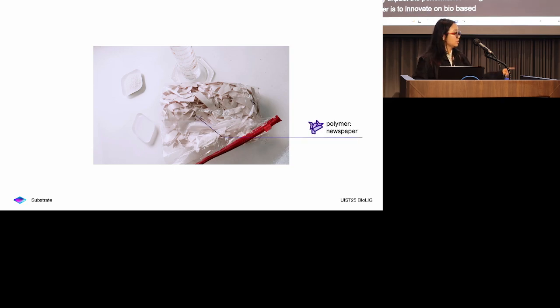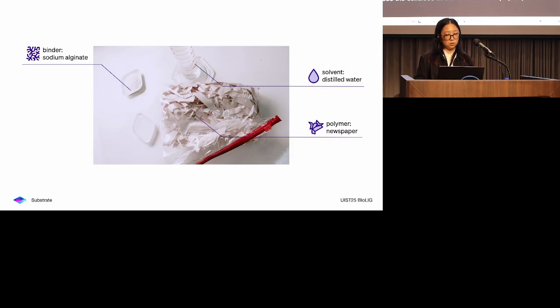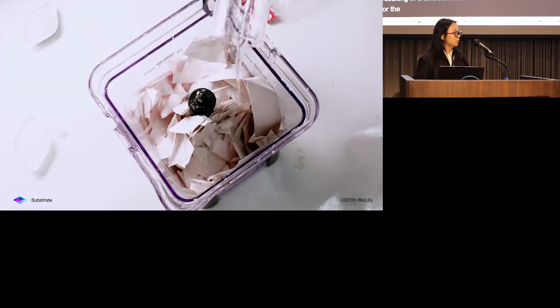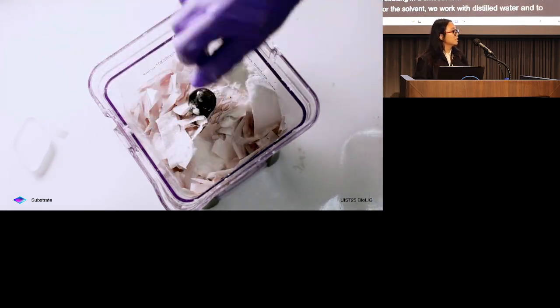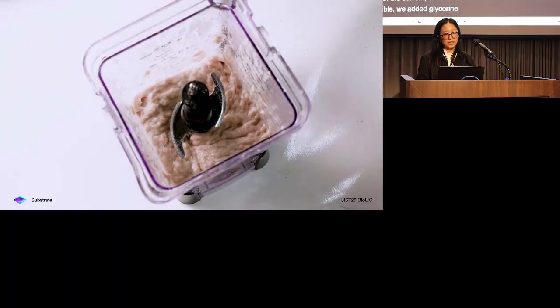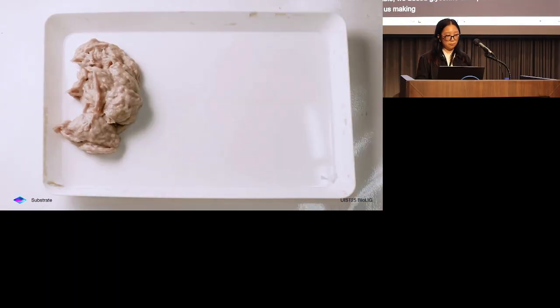In this picture, you can see the cellulose in the form of newspaper print, which has short fibers resulting in a smooth final surface. For the binder, we use sodium alginate. For the solvent, we work with distilled water. And to keep the materials flexible, we added glycerin as a plasticizer. Here's a short video of us making the material, mixing it together in the blender to create a slurry, which is then evenly spread onto the tray for drying.